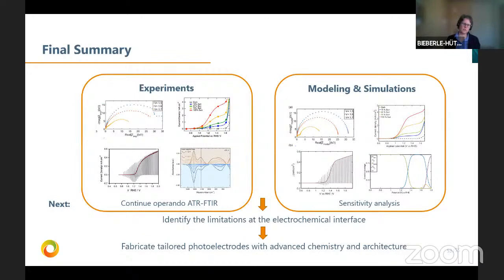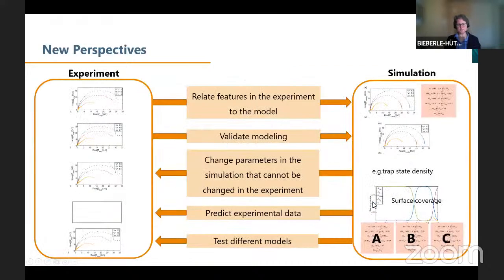Yeah, as I said, what we have done is we have done experiments in modeling. We can do similar measurements. You see here surface coverage calculations that come out with our modeling approach. And you see here, we are not so far yet with the ATR-FTIR, but this is actually where we would like to connect these two. We continue with these ATR-FTIR measurements, and especially here we do a sensitivity analysis.